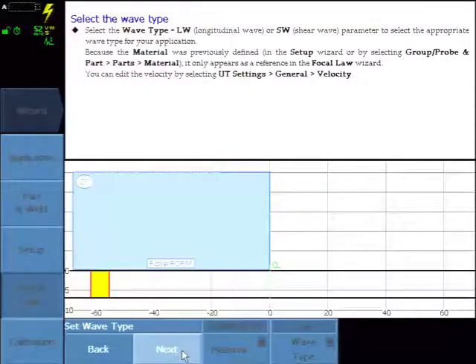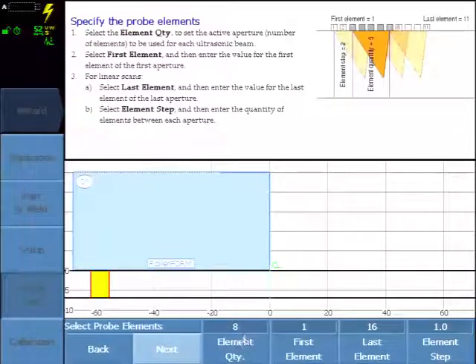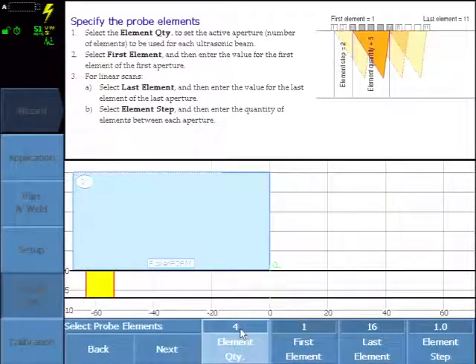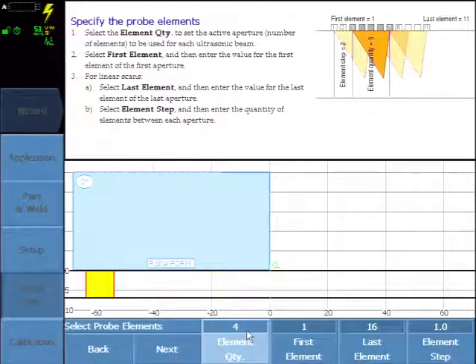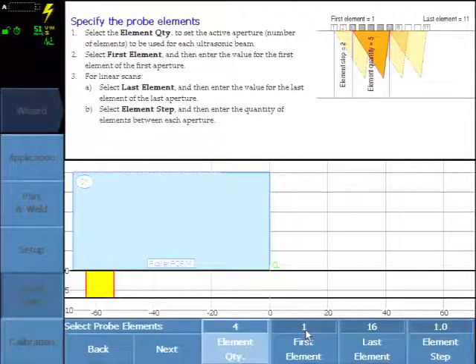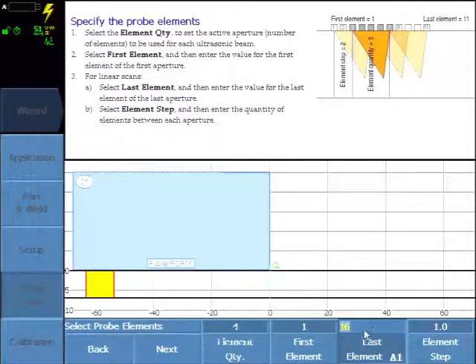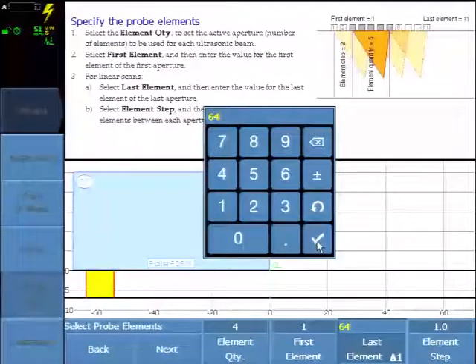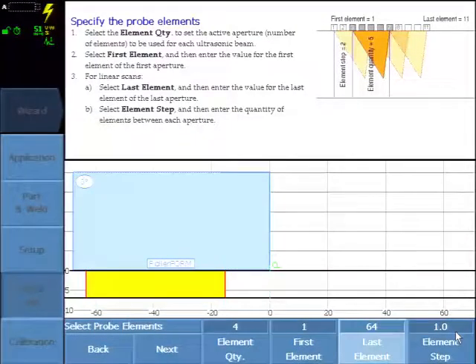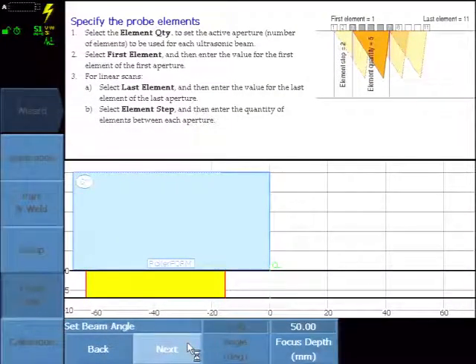We're on the first leg. We'll use a default element count of four. Four elements per A-scan or aperture. This can be increased depending on the thickness of the component and best results. Start element one and this is a 64 element probe and we'll use the entire probe. Every A-scan is going to step one millimeter and select a shallow focal depth.